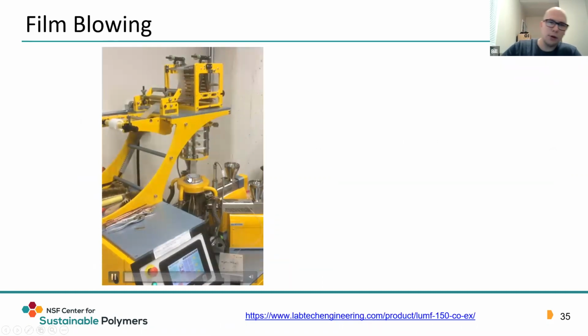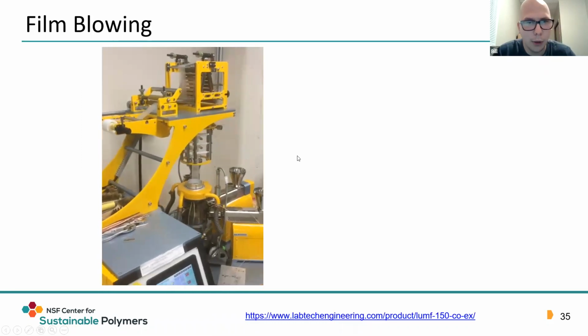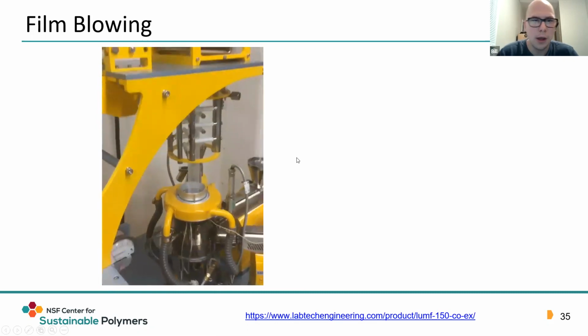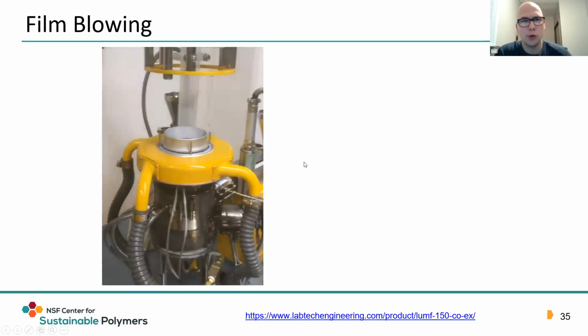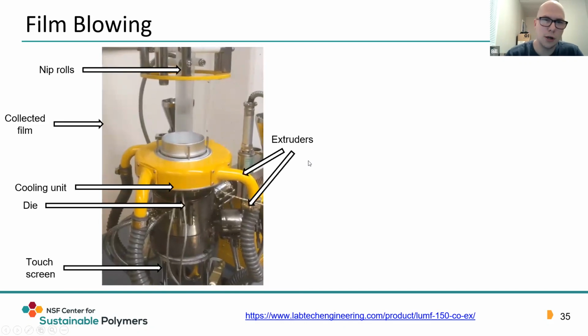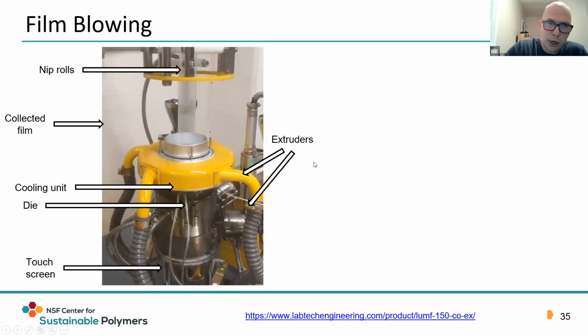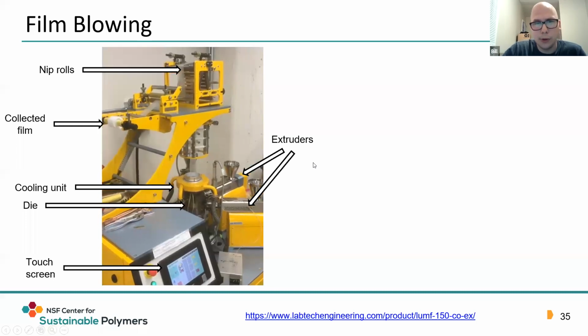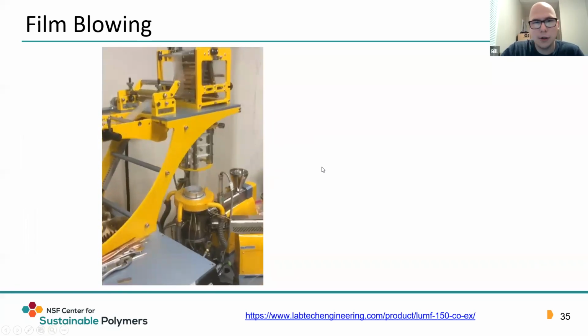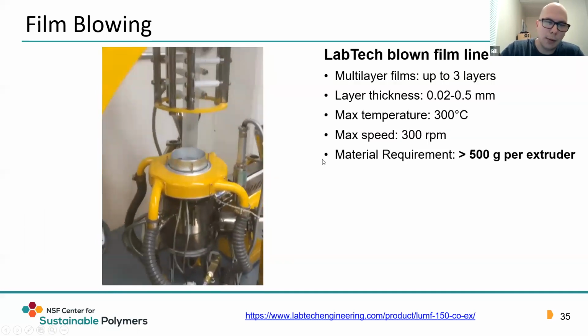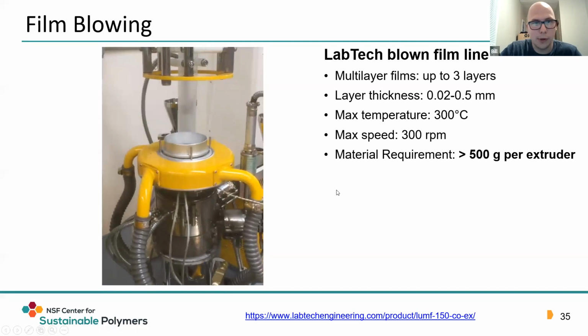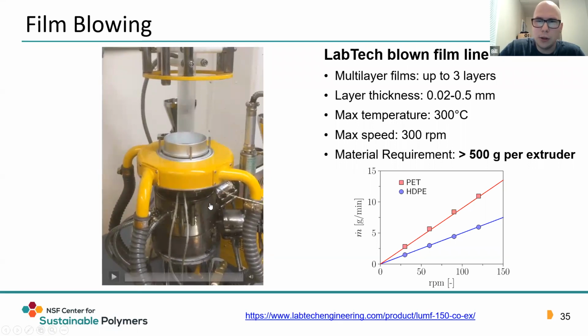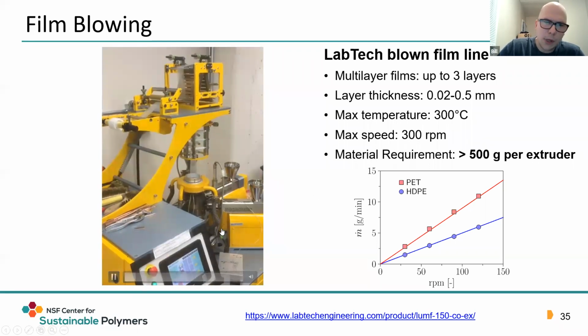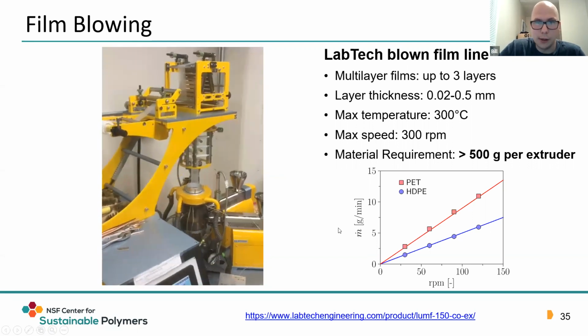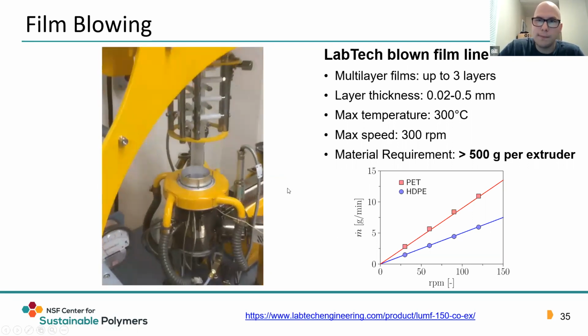This last, more unique system we have is this small scale film blowing system. It works on a similar capacity as the multi-layer co-extrusion, about 500 grams per extruder. We're able to have 3 extruders here, so we can layer 3 polymers together, either as a tie layer for compatibilizing or adhering incompatible polymer systems together. You can look at effects of blow up on your system, and we have pretty good control over the relationship between the flow rate and the operating speeds of the equipment.